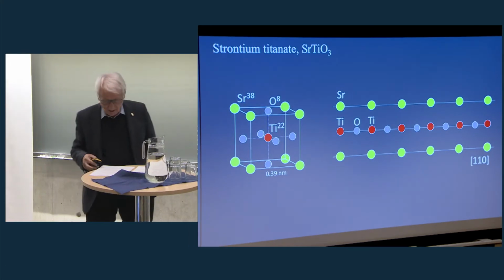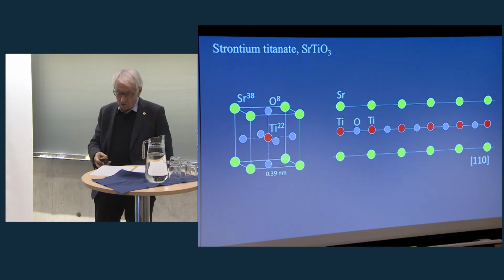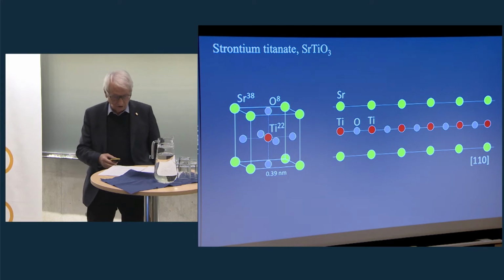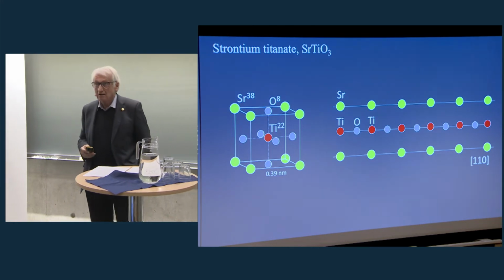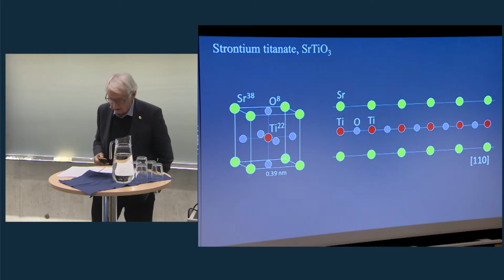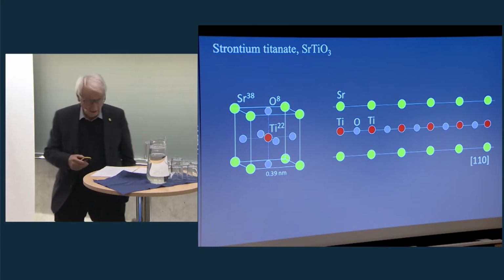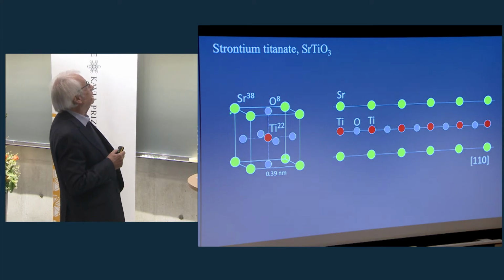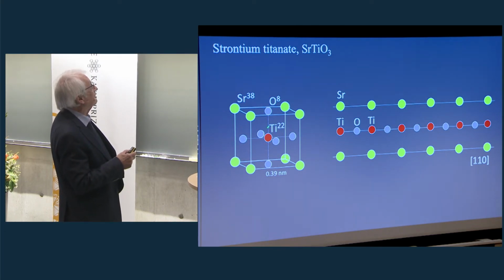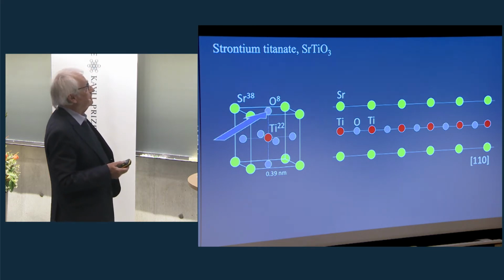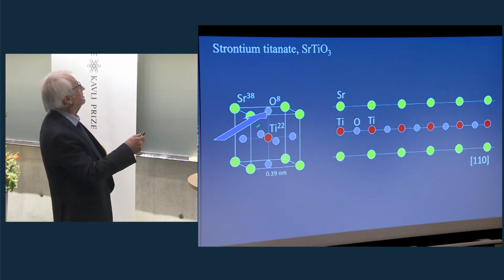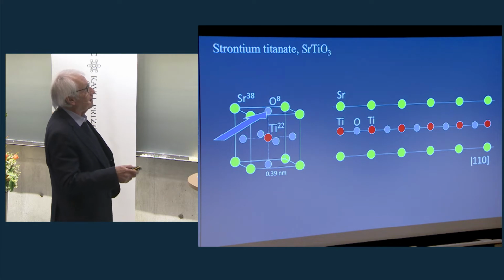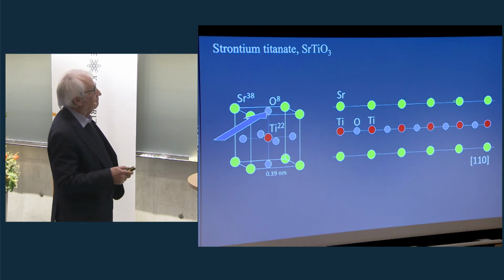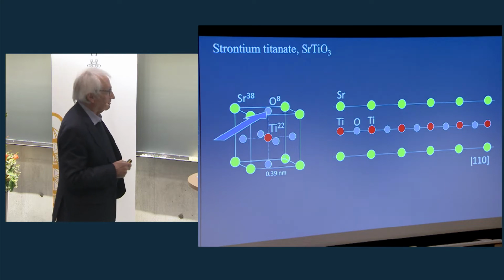So now let's start as we did it 2.5 decades ago with strontium titanate, which became more or less the Drosophila of material science, aberration-corrected electron microscopy. We have the individual atoms here in this ball and stick model, strontium, oxygen on the faces, and in the middle we have titanium. In all the images you are seeing, we will look along this direction. That means we get a projection which looks like this. So we have strontium, and behind each strontium is another oxygen. And that means we have strontium rows, and we have rows where we have titanium, oxygen, titanium, and so forth.